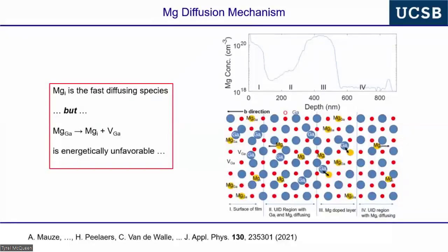For those of you who learned about diffusion, the primary diffusion mechanisms are either vacancy-assisted diffusion or interstitial diffusion. This is what you learn in undergraduate materials science. At these temperatures, we could never account for the diffusion by vacancy-assisted diffusion, which would be gallium vacancies. This never worked. The magnesium interstitial is a small cation and actually a fast-diffusing species. But the problem is to take a magnesium on a gallium site, place it on an interstitial site, and create a gallium vacancy.